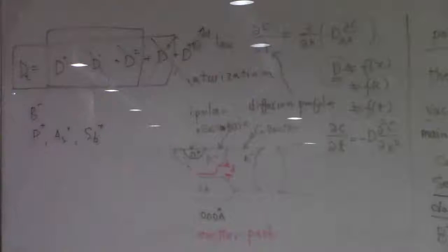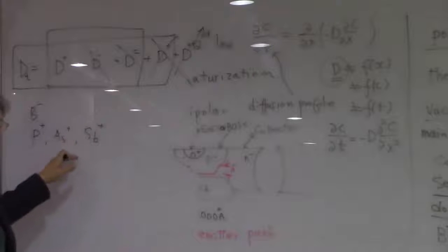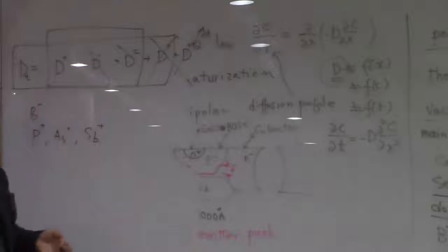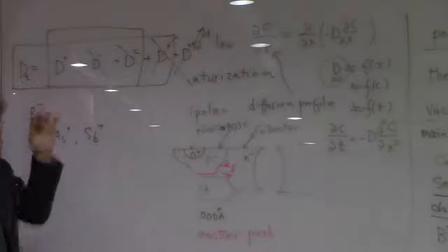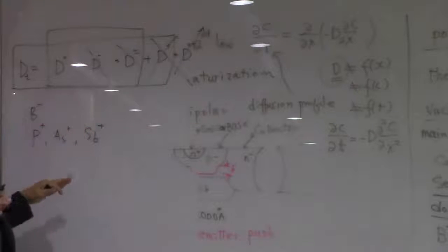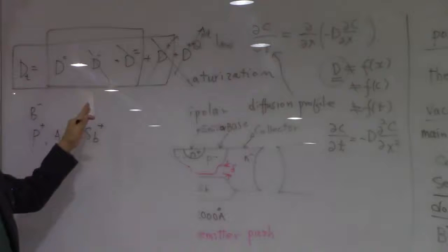And we have 3 terms, a little bit more complicated than the case for boron. But even if we have these 3 terms for the n-type dopants, depending on the temperature and the doping concentration, among these we have a dominant species, and we don't have to worry about the other terms except the dominant terms to get the diffusion coefficient, right?